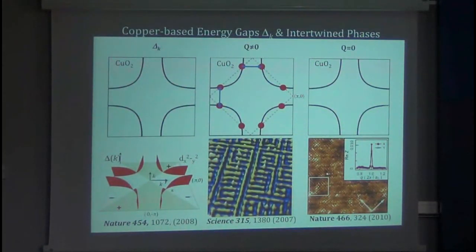Okay, so here's your first homework problem. You need to remember this slide. This slide is a summary of the key things that we know about the cuprate electronic structure. It has a dx squared minus y squared superconducting energy gap on a very simple Fermi surface, which is a single hole-like pocket around the (pi, pi) point. Coexisting, it has a broken translational symmetry finite Q state, which is actually associated with this scattering process. And coexisting, it has a Q equal to zero intra-unit-cell broken symmetry state.